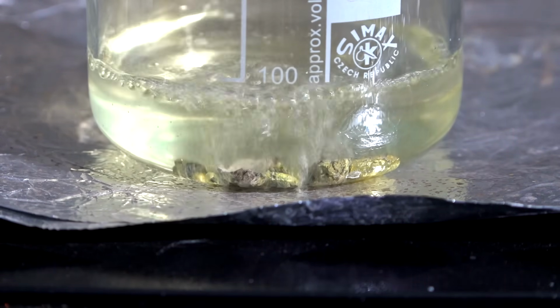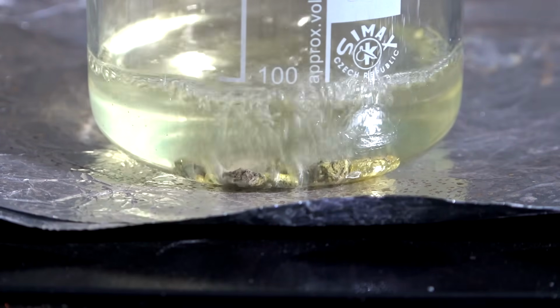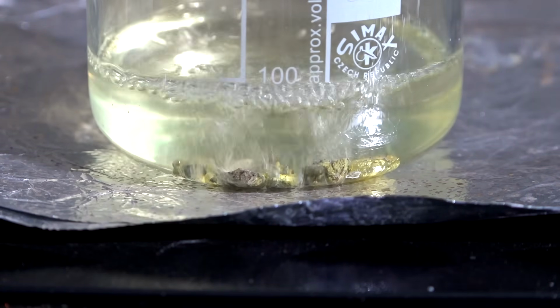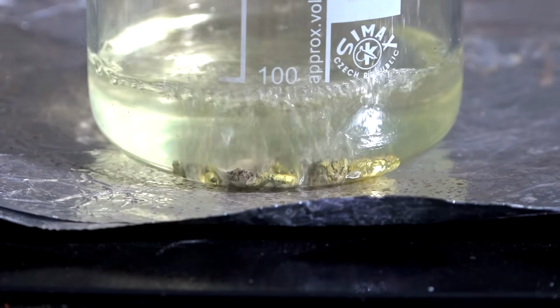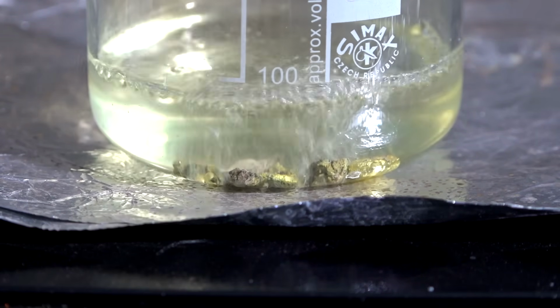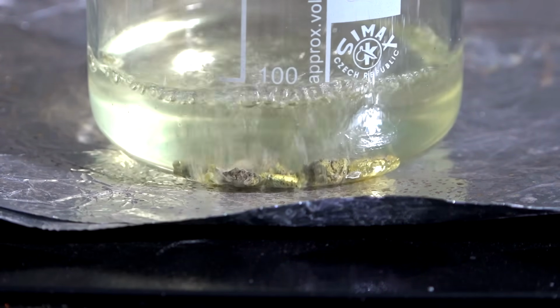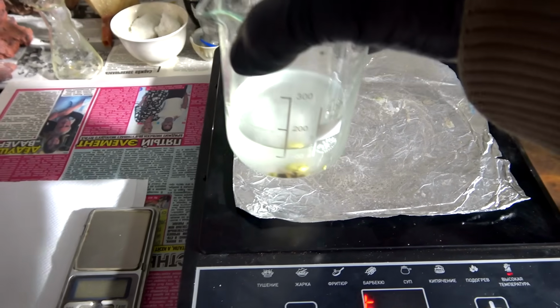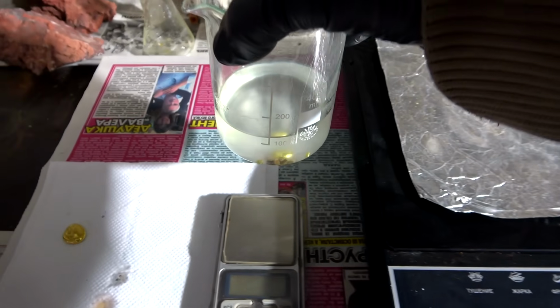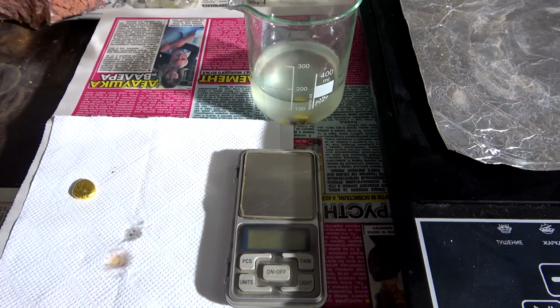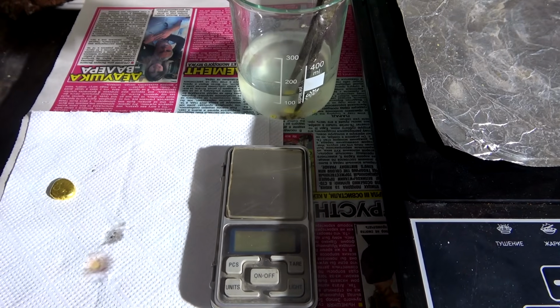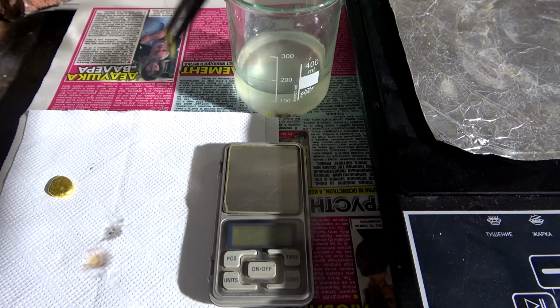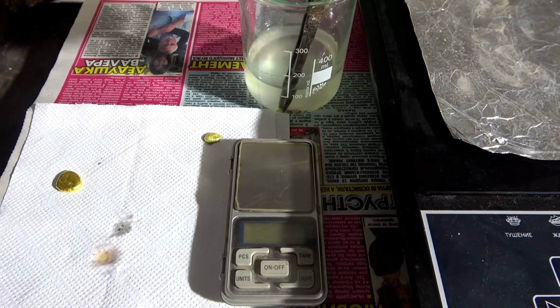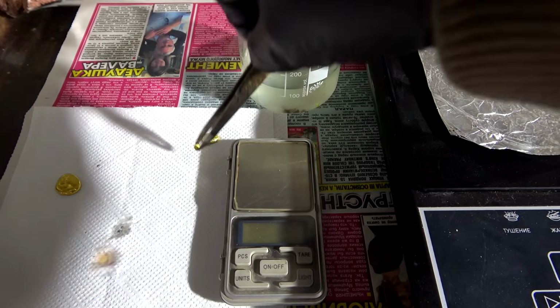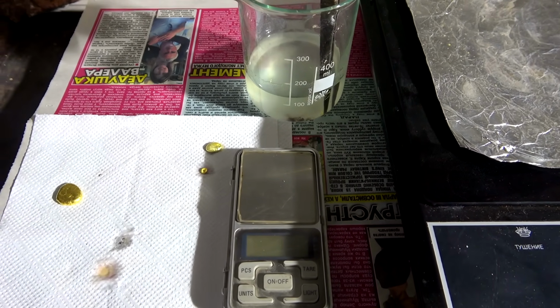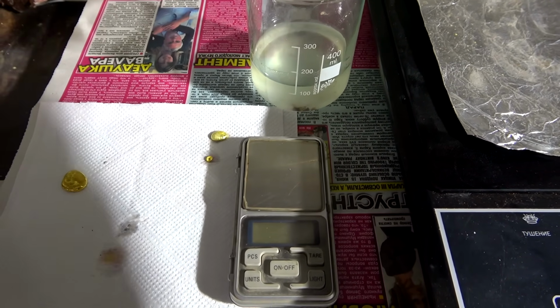I boil all the resulting pieces of gold in diluted nitric acid, in order to get rid of lead oxides. This takes 10 minutes. Now I can remove these gold pieces from the beaker and weigh them. This time I have 3 pieces, and melting them into a single bar won't be difficult.